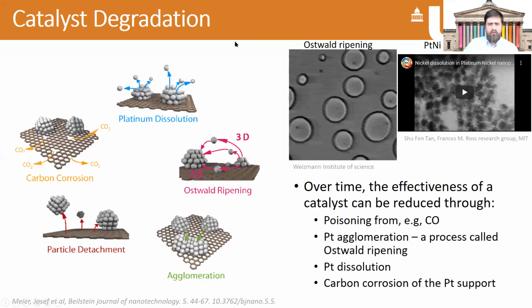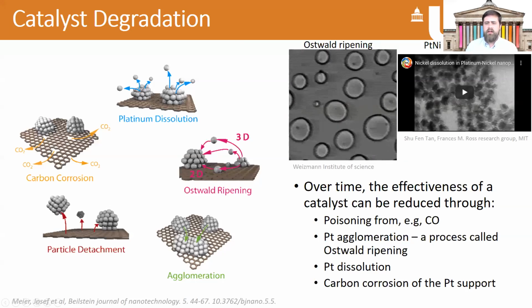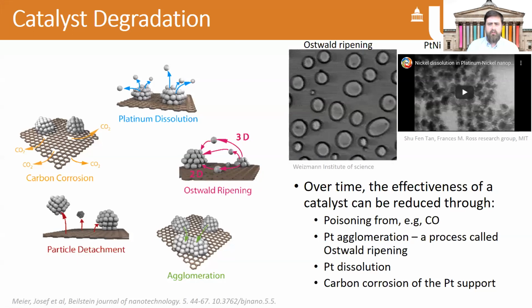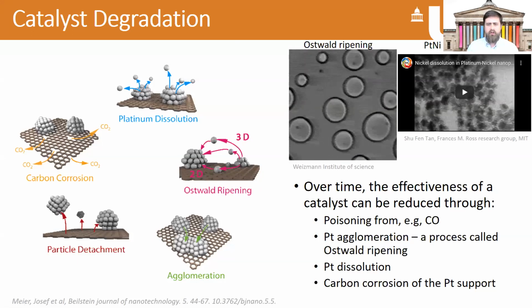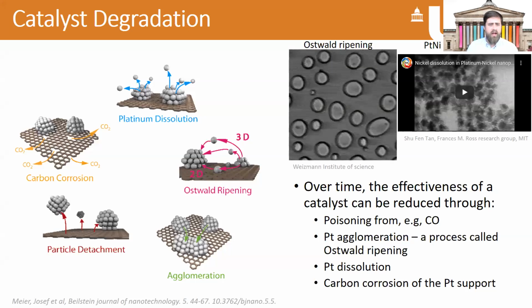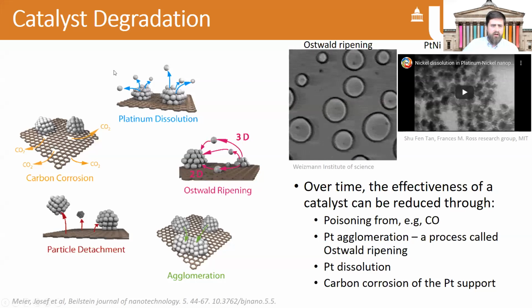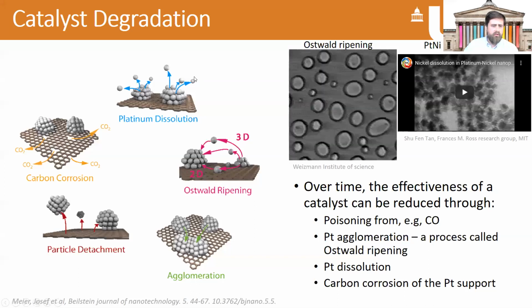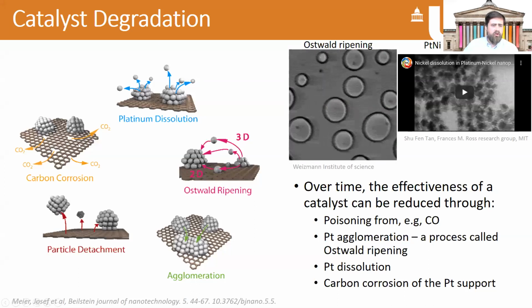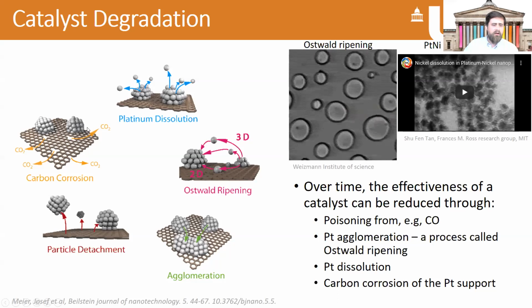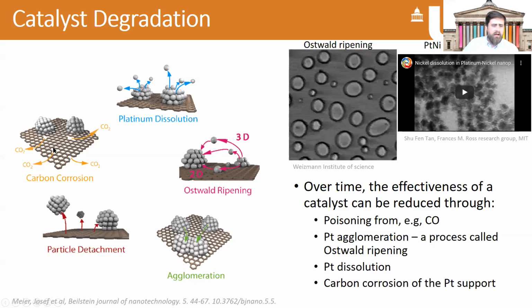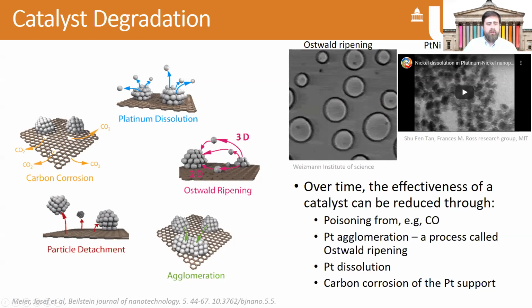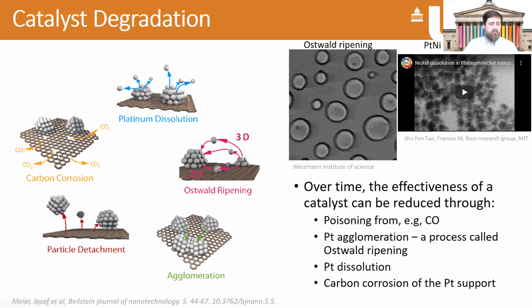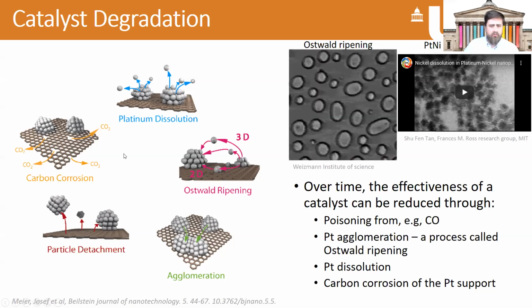Once you've got a good catalyst, you obviously want it to last for quite a long time, and actually they can degrade over time, although some of the degradation that occurs in fuel cells is perhaps a little less of an issue than in lithium-ion batteries, for example. But there are mechanisms by which the catalyst can degrade. So you can see on the left-hand side here lots of different ways that this could happen. You can have the platinum literally dissolving into the electrolyte. You can have the carbon corrosion occurring. Sometimes this is catalyzed by the platinum that sits on the carbon surface. That can introduce defects into your carbon, lower the conductivity of the carbon, and eventually just erode away the carbon so much that you don't have the same sort of structure there as well.